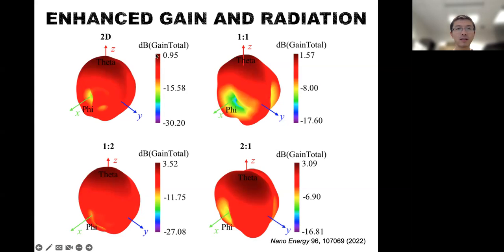In a 2D case, the peak gain is about 1 dB, but if we turn that to a 3D antenna, it gets increased by about 50%. But if you further change that from symmetric to asymmetric design, the peak gain gets increased by about another 100%. So that's really the reason why we're able to achieve even better performance with a small change in the shape. And of course, we have not explored all of the parameter space in the 3D antenna, but this opens up a totally new area for us to explore. You can do a lot of different designs and be able to further enhance the performance way beyond what we have demonstrated here.